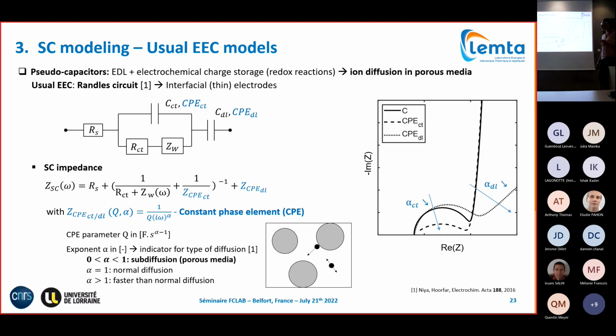Another thing is that for those who are familiar with EIS, very often you find what we call constant phase elements instead of real capacitances. Constant phase elements introduce an exponent alpha; the CPE has a complex capacitance parameter and your exponent alpha. This exponent alpha will result in a deviation. If you have alpha in the pseudocapacitor of your Randles circuit, this will result in a depressed symmetric half loop. And if you have it in the CDL, the double layer component, this will result in the deviation of your low frequency line from the vertical line. In a practical part, this is used to better fit the spectrum.